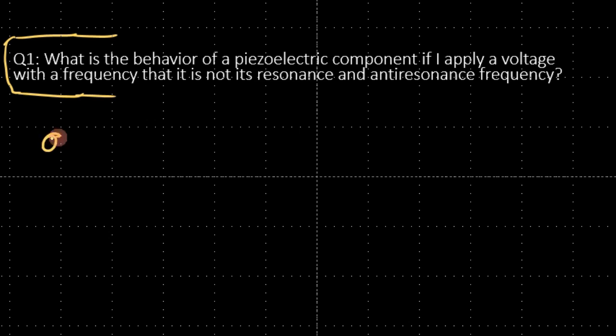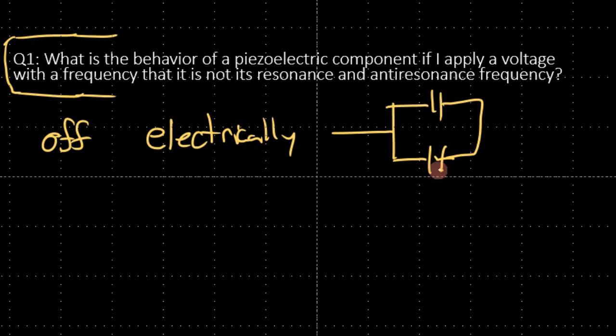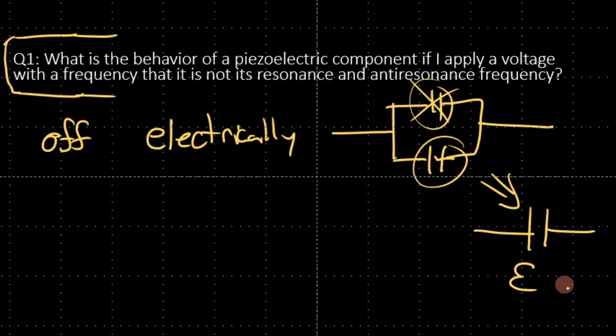If it's not resonance or anti-resonance, firstly it's off-resonance. At that frequency electrically, you will get something like the effect of two capacitors in parallel. One capacitor will be representing the effect of the piezoelectric portion. If you completely clamped the material you would not get this, but you would get the effect of this capacitor, which is the intrinsic dielectric response called the clamped response. Essentially you would then get the effect of a single capacitor governed by the permittivity, which you're mostly going to see in the company-provided data - the permittivity under constant stress.